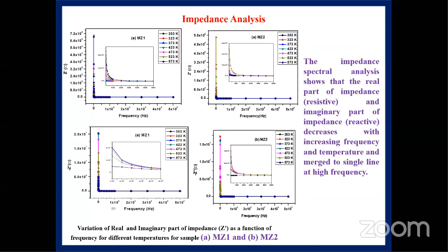This is impedance analysis. From the figure, the impedance spectrum analysis shows the real and imaginary parts. The real part of impedance is resistive, and the imaginary part is reactive. You can see from the graph that the real and imaginary parts of the impedance decrease with increasing frequency. At higher frequency, all the temperatures merge to a single line.